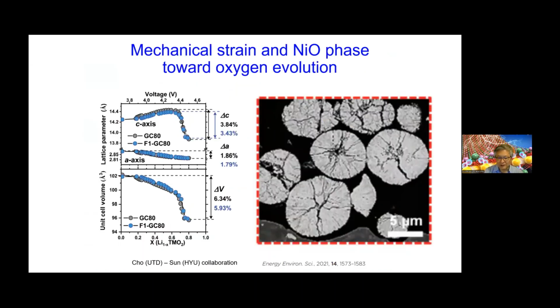But the second issue is that even if you do the coating of the cathode material, the cathode material itself, during the charge-discharge cycle, goes up to 6% of volume change. The oxide is ceramic. Ceramic is a brittle material. So the typical macroscopic brittle material fracture strength is about, if you have a strain of 0.1%, then you tend to break. 0.1% of strain, volume-wise 0.3%, but this is substantially higher than that. Typical glass breaking, the ceramic breaking strain. So it's not surprising that during the cycling, the ceramic particles are breaking.